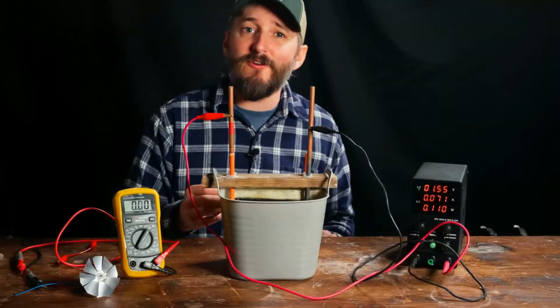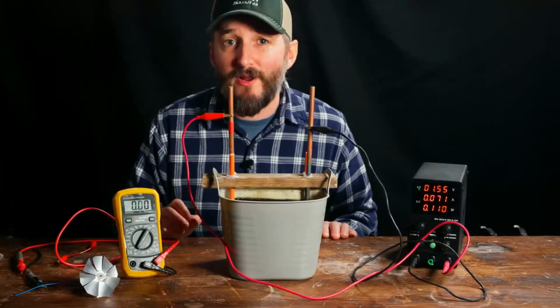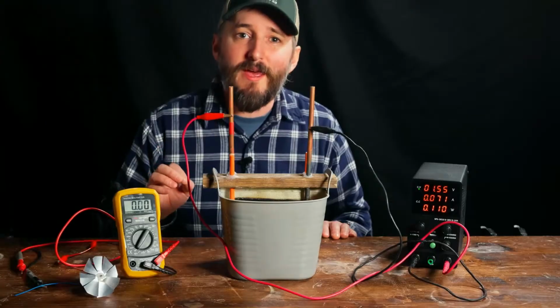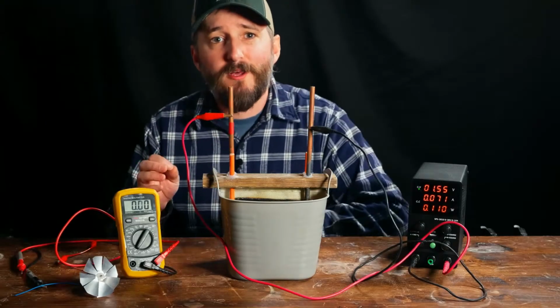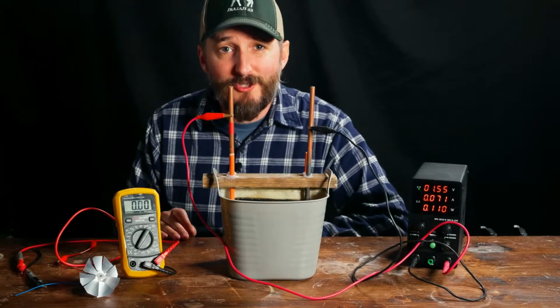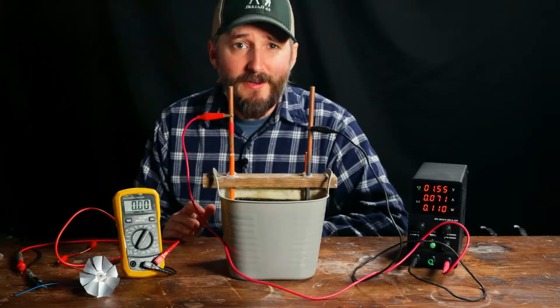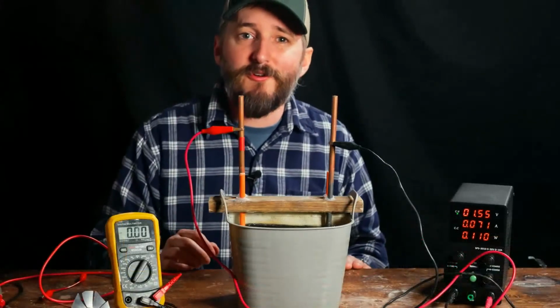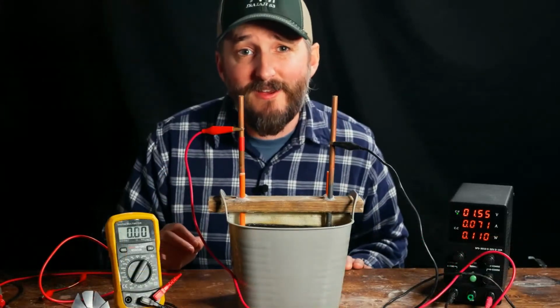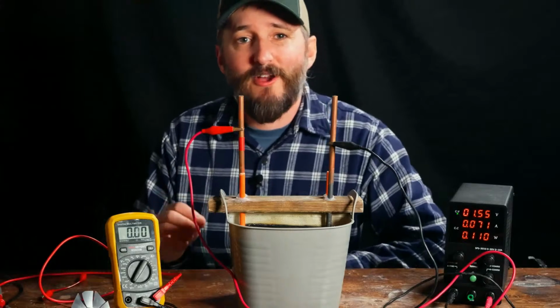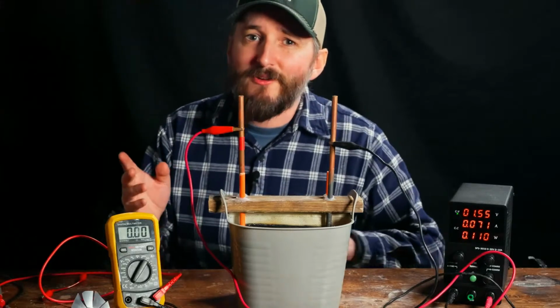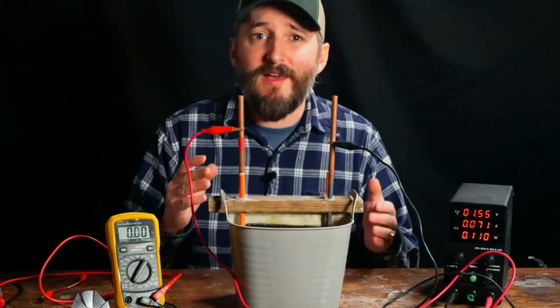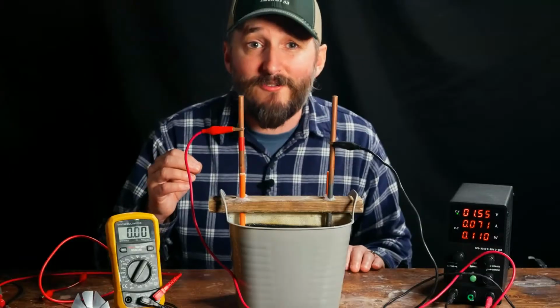Increasing the amount of iron sulfate in the electrolyte to 300 grams per liter will double the amperage, as long as you keep the battery warm enough for the extra iron to stay in solution, about 70 degrees Fahrenheit. You can push the amperage even further by adding sulfuric acid to the cell, which greatly increases electrolyte conductivity. But doing so, of course, requires more safety in how these batteries are designed and stored.